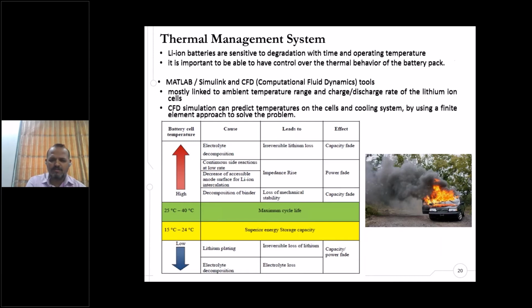Then if your battery goes under a thermal issue, it can propagate into thermal propagation. Then lithium plating, which is irreversible loss of lithium, and capacity fade, as well as loss in the electrolyte decomposition at lower temperature. So always, for your battery pack of higher kilowatt hour, specifically India specific, you can have a good cooling system, so you can prevent thermal runaway issues over the period, because during charge and discharge heat is generated, and if the outside temperature is higher, you have to control your cell temperature.